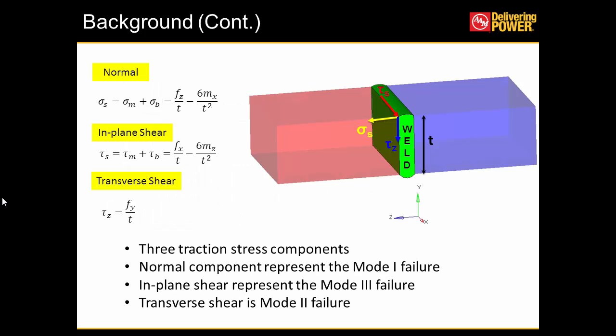So here I have an example of a butt welded arrangement. We have a hypothetical crack plane which is represented by the XY plane, and the very complex stress distribution because of the notch effects can be simplified to a very simple stress state, which can be represented by a membrane and bending component. So there are three kinds of traction stress components. There is a normal structural stress component, there is in-plane and transverse shear. The normal component represents the mode 1 failure, the in-plane shear represents the mode 3 failure, and the transverse represents the mode 2 failure.